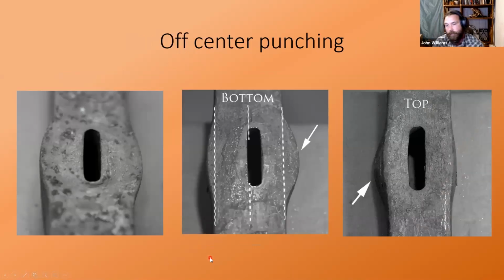It's important when you're doing your layout, especially at the beginning. This is one area where you really want to take some time. If you end up off center, what happens is you have more resistance on one side, on the thick side, than you do on your thin side. And because this side is resisting, the majority of the distortion in the stock will occur on the thin edge. So you're going to get a bulge occurring on the thin edge, and the thick edge will stay put for the most part. That's not the end of the world.